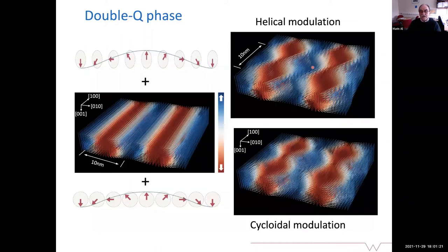And then we can imagine that we have the vortex here, which is this one. Along the vortex in this direction, we can have either a helical modulation, which means we have a helix going along the core of the vortex and twisting the polarization, or we have a cycloidal modulation. Analyzing carefully what it would be, we arrived at the conclusion that it should be a cycloidal modulation.